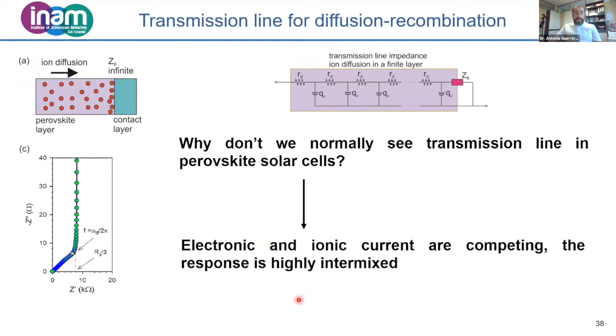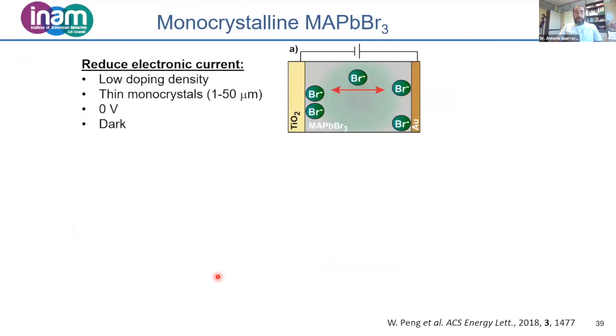And the answer was simple: we were observing the mixed electronic and ionic current, and as they were competing, they were both highly intermixed. So then what we did was to design a device architecture where we would minimize the electronic current. So we use methylammonium lead bromide monocrystals without spiro.